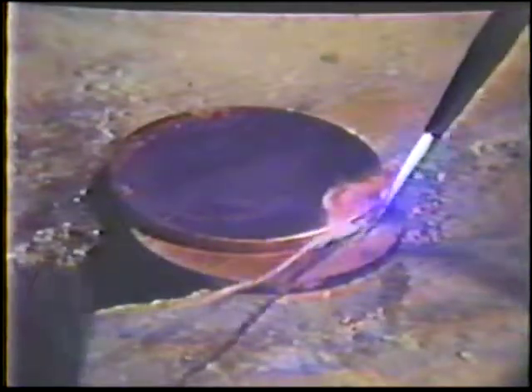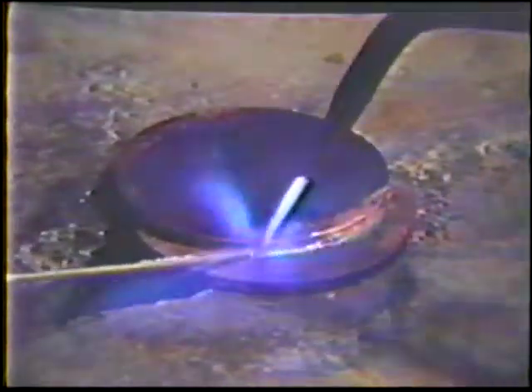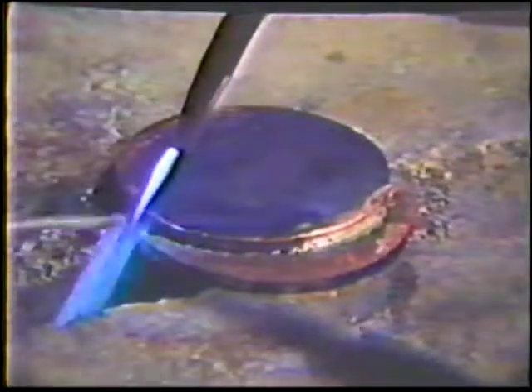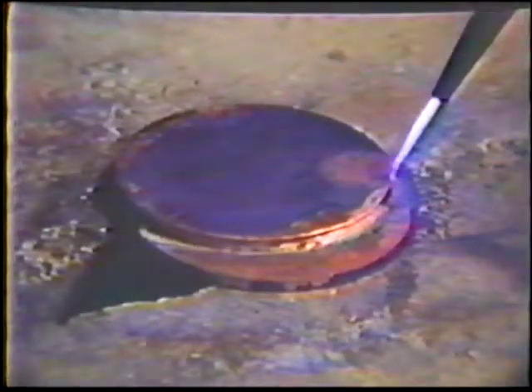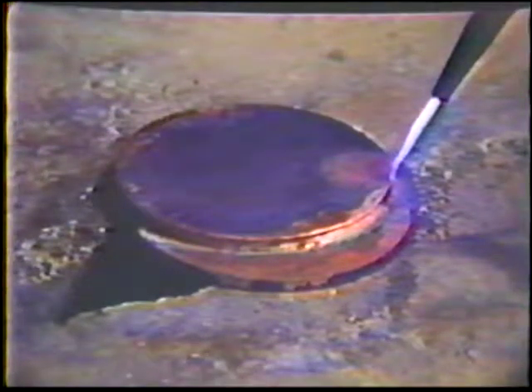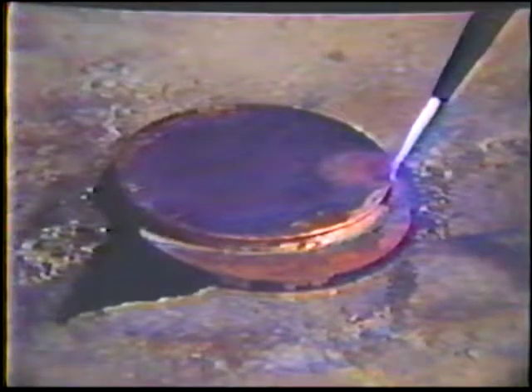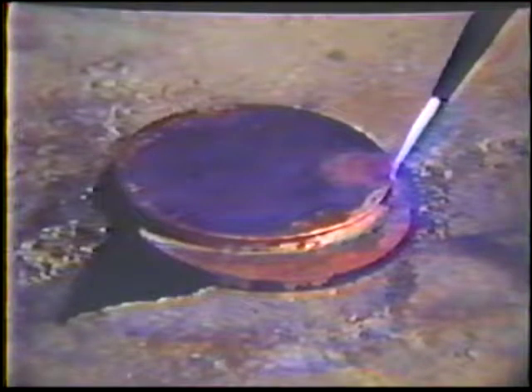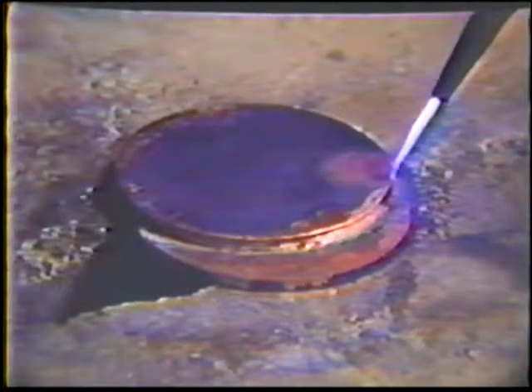When the metal is hot enough, remove the flame and wipe the tip of the rod across the edge of the joint at a rate that will leave a small fillet at the corner and supply enough filler metal to be drawn through the joint. Allow the part to cool and inspect the joint.